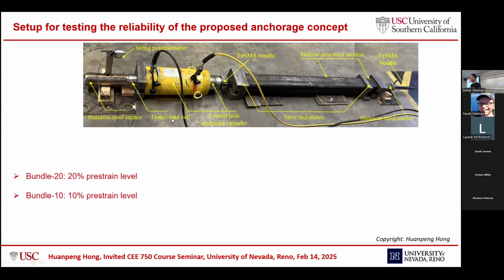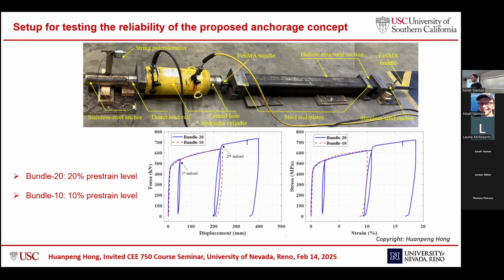To test the reliability of the proposed anchorage concept, we used a two-way center hole hydraulic cylinder to stretch the bars. Both sides are welded by the proposed anchor, and in the middle is the iron SMA. We stretched these bars to 20% and 10%. We did 2 tests. Here I need to emphasize, maybe from this figure you cannot see how large this is, but when I was working on site, this was around 12 feet, and the force here is more than 200 kips. When we were doing this, we were so nervous, maybe we were the first to do it, and if the bar structure failed, it would be like producing some kind of bomb. But fortunately, after this test, for both the 20% pre-strain and 10% pre-strain, the bars are still intact.